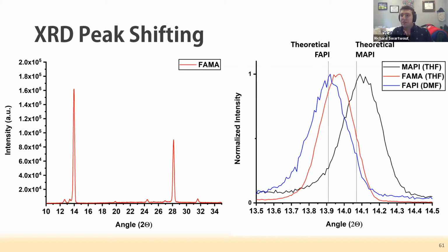But I do want to point out that THF-based routes, which were used here, both the MAPI and the FAMA recrystallized film have about a quarter degree shift to higher angles. This means we might actually be having a near full conversion of formamidinium, but that peak alignment might be due somewhat to the solvent, although this hasn't really been studied.